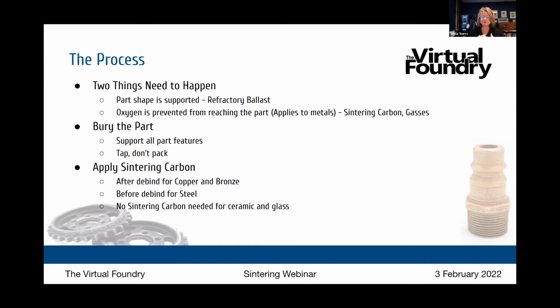The ballast is reusable. The sintering carbon is designed to get consumed, so that can be filtered and you can reuse the part that remains, but that is designed to be used up in the process. So that's a consumable item. You're going to bury your part, and Brad will show us this in a minute, in that refractory ballast, making sure that all of the part features are supported. You're going to tap that ballast in there, not pack it heavily, so that part still needs to be able to move and shift as it shrinks on itself. So it's important that it's supported, but can also move.